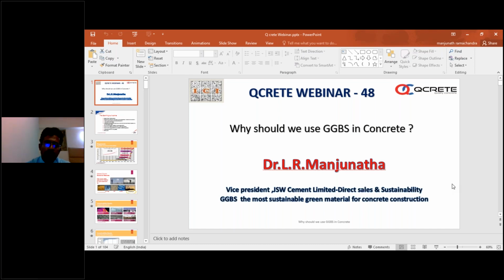With PSC also, by using ultrafine material like QCrete ultrafine GGBS or ultrafine fly ash, by tweaking 3 to 5%, we can achieve that strength parameter. We need to add ultrafine material to improve the strength of the concrete when using PSC cement. So mixtures can be done using PSC. There is no problem at all. Okay, thank you so much, sir.